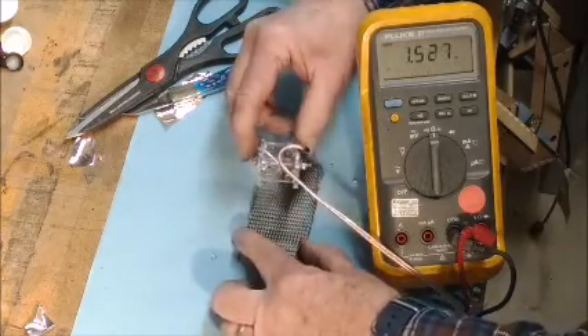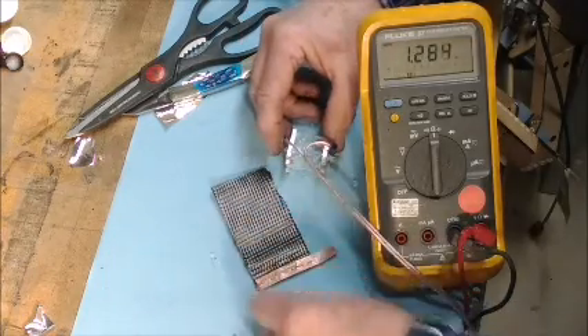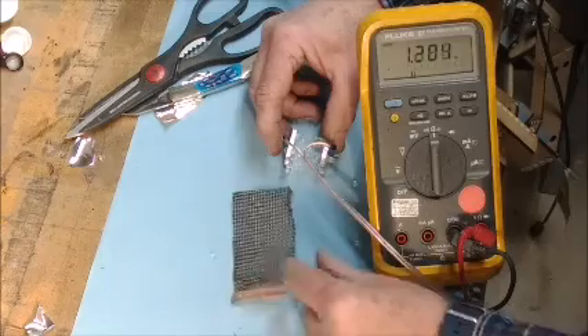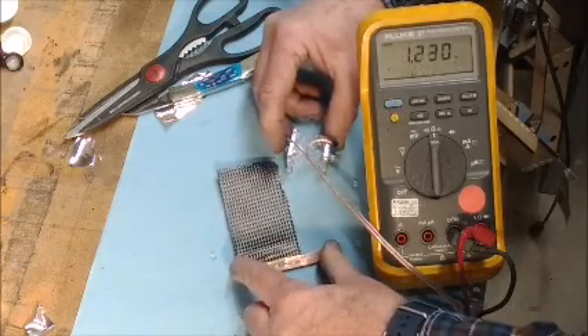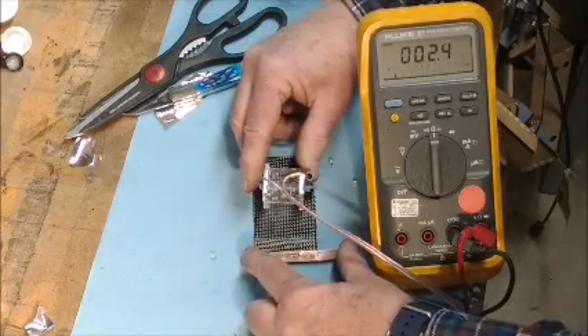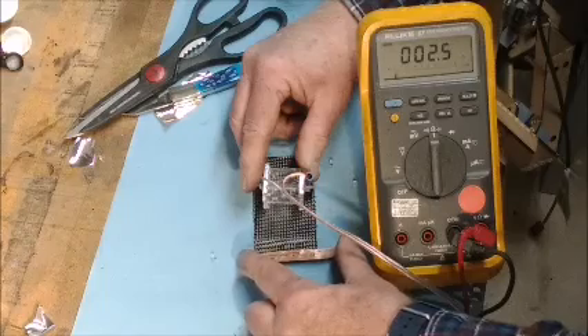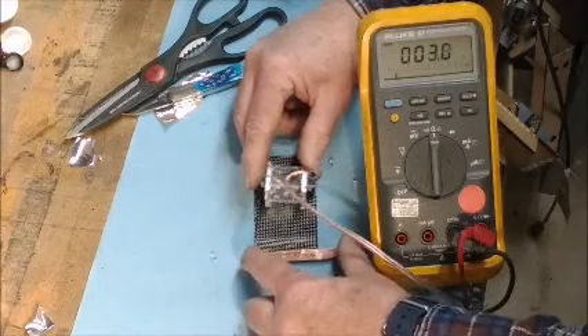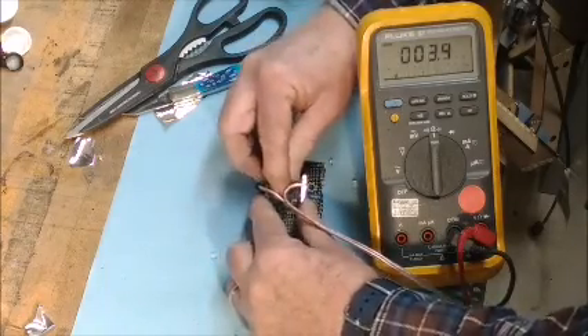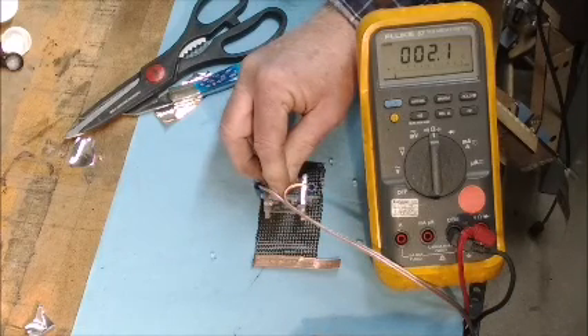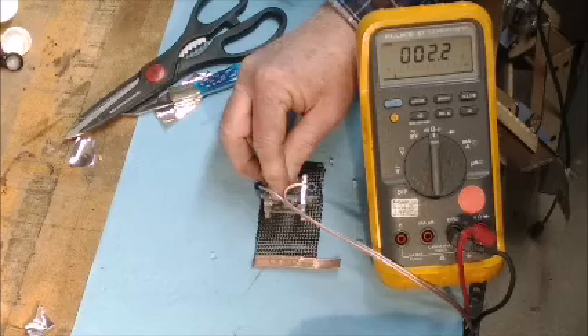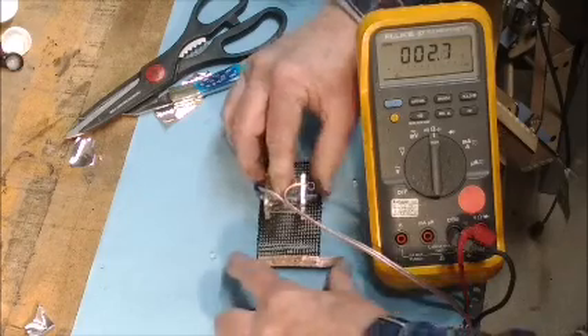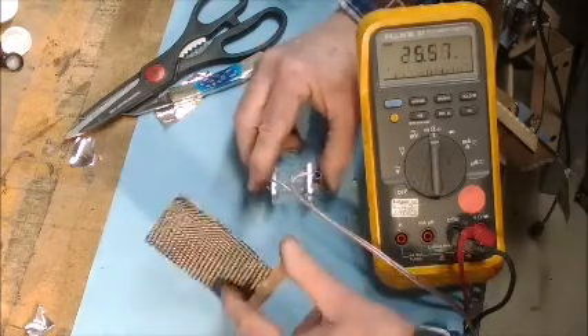But anyway, one of my earlier videos showed the process to make these little test strips. What kind of resistance do we get here? So 2.4 ohms, 2.5 ohms per square. It's somewhat dependent on how much you push down, because now I'm sinking the surfaces of the probe into the cloth, but that's 2.2 ohms, and that's really good.